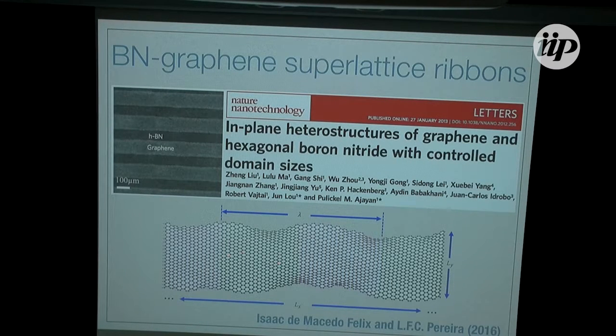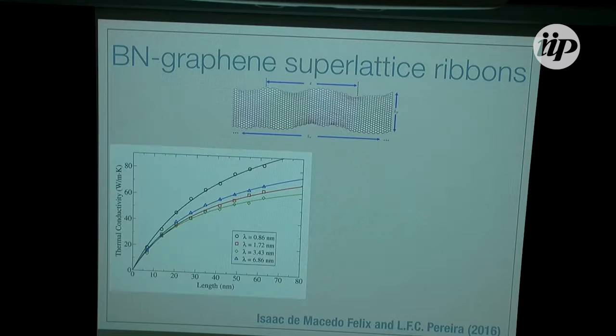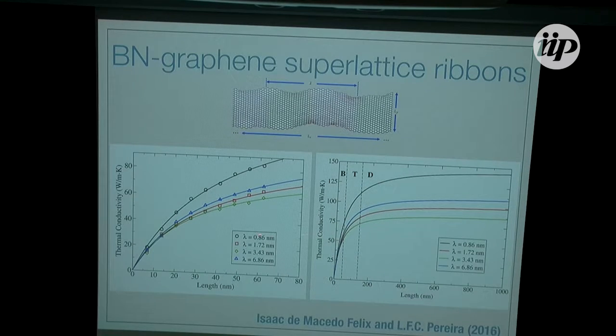Another thing we did recently was mixing graphene and BN. This was produced experimentally a few years ago in a group, and they just looked into producing this thing and a few physical properties. Now what I've been working on with PhD students I'm supervising is the thermal conductivity of this type of material. And what we see here is that as we change the size of the graphene and the boron nitride patch, we get different values for the thermal conductivity of the ribbon.